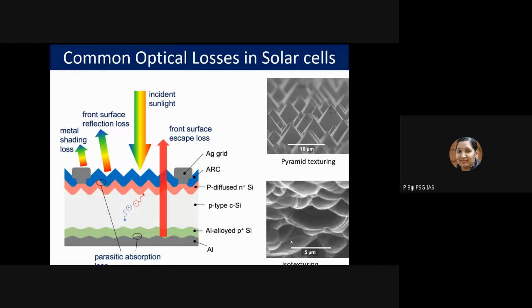Then the surface texture not only reduces the front surface reflection, but also contributes significantly to light trapping, by coupling the light into solar cells at an oblique angle. Because of the internal scattering at the interfaces, some photons make multiple passes before escaping from the solar cell. So two types of texturing have been adopted by the industries.